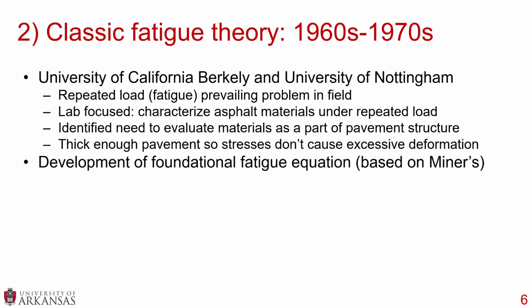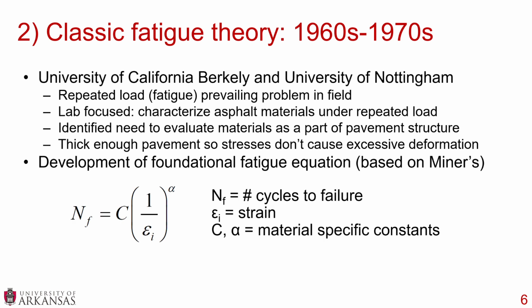And what they did is they started the development of foundational fatigue equations, and they based it on Miner's hypothesis, which is where the number of cycles to failure, N sub F, equaled a constant, which is a material-specific constant, multiplied by 1 divided by the strain, and that 1 divided by the strain was raised to another material-specific constant power.